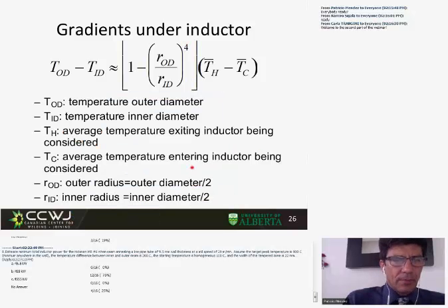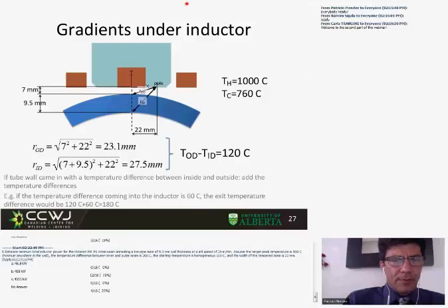So this formula, which is a very big approximation, gives us a sense of what role the gap plays, and what role the width of the temperate zone plays. It helps us think about the poles of the inductors. When we buy the inductors, we seldom ask these questions of the supplier. But sometimes it might be good to have this in mind, to make sure we don't have an inductor that is either too narrow or too wide for the diameter we need.